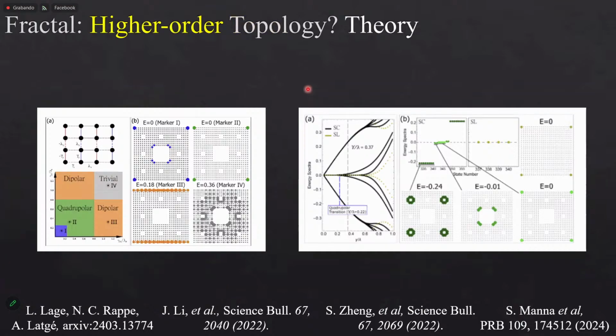Also, if you look at this higher-order topology that I showed you for bismuth, it also occurs. There have been works from other people, but also this one was by a group in Brazil, from Lucas Lage and Professor André Latgé from the Federal University Fluminense in Rio, Niterói. And they show basically similar things, that you can have higher-order topological phases and corner states. Something that's interesting here is that they show that the states live in corners, both the outer and inner corners, and also inner and outer edges of the system, and they appear at different energies. But I'm not going too much into detail on that.